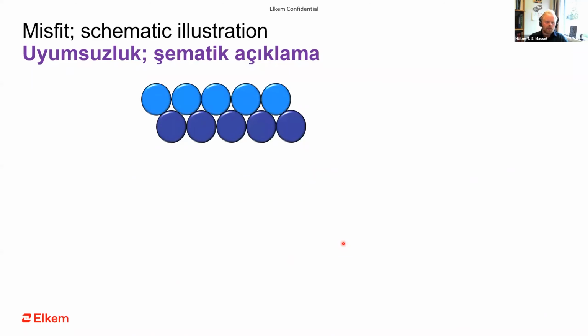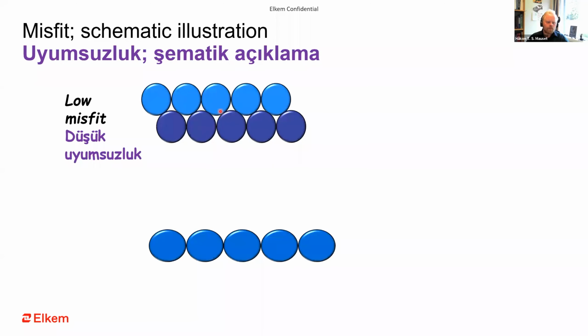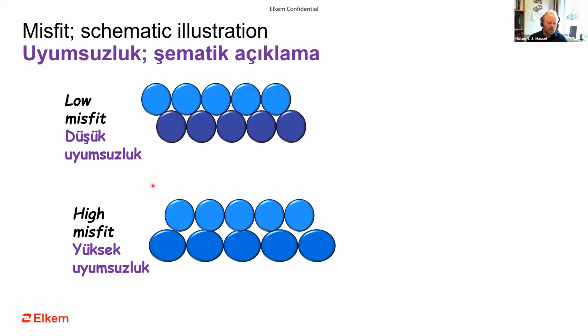But then the concept of misfit, as I said, can be a bit difficult to understand, but if you look at these simple spheres here, they have the same diameter, all of them. And we see that here we have one row, and then the next row fits excellently in the voids here. And we have a repeating pattern. So here we have a low misfit. These spheres fit well together. And here we have an example of high misfit. Here you see these spheres have a different diameter than these ones. And we see that this row of spheres does not fit well with this row. We don't get the repeating pattern. There is a difference in the voids between them.